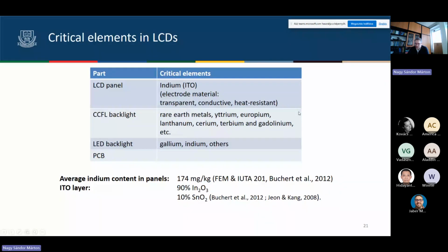We measured the composition of them and what is inside this material. We realized that indium tin oxide is there. Indium tin oxide is the electrode material. Why? Because it's transparent and conductive and heat resistant. That's why this quite expensive material is used in the LCD display panels. In the former CCFL backlight, we find a lot of rare earth metals. And in the nowadays used LED backlight, gallium and indium and also other interesting elements were found. And of course, in the printed circuit boards, there are also interesting elements.